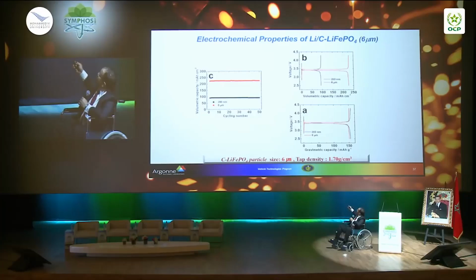So how about the performance? This is the gravimetric energy density of a 200 nanometer iron phosphate versus 6 micron. Obviously, it's gravimetric, so the capacity is the same. But look at the volumetric, where the density plays a big role. You can see we almost double the volumetric energy density. Now we are very competitive with the oxide.